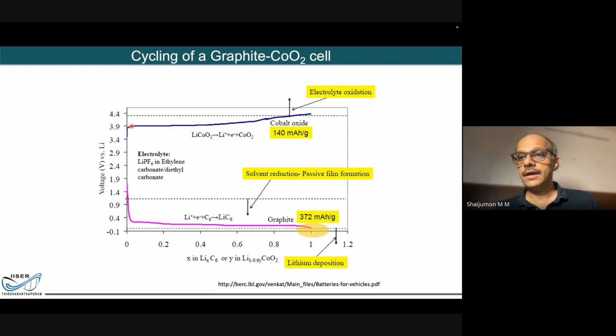The blue line stands for the reaction which is happening at the cathode end, wherein you can see that, let's say I'm charging the battery, the lithium ions are moving. Getting charged means there is a voltage plateau here, which corresponds to this reaction, which I said, lithium cobalt oxide releasing lithium ion plus electron, leaving the cobalt oxide layer there. At the same time, these lithium ions are moving through the separator and electrolyte and getting intercalated into the sheets of graphite. And that process is shown in this pink plot here.